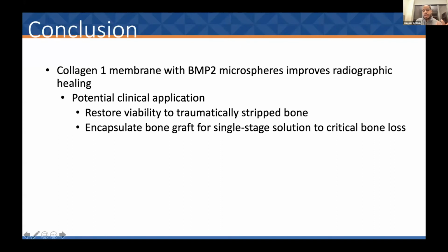So in conclusion, we established that a collagen type 1 membrane with BMP microspheres improves radiographic healing. And our potential clinical application is that we can restore viability to bone that's been damaged, potentially. And then also we can incorporate this membrane into a synthetic scaffold that has some strength and compression to potentially offer a single stage solution for critical bone loss in our patients that relies on healing.